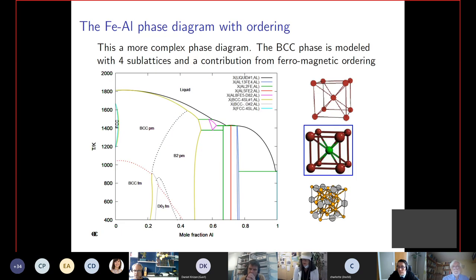So to a bit more complex system, if you take iron aluminium, iron dissolves quite a lot of aluminium in the BCC structure, and you have also a magnetic transition. So you have a ferromagnetic state at low temperature, a paramagnetic at high temperature. You have an ordering to a B2 structure, which is this, where you have a central atom which is preferred to be different from the other ones.